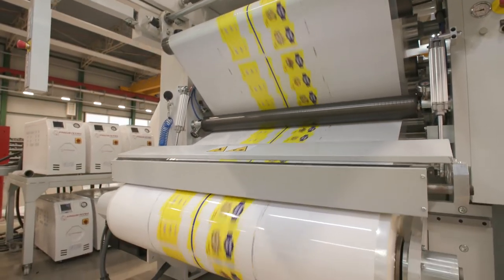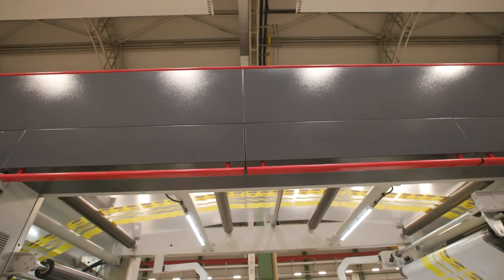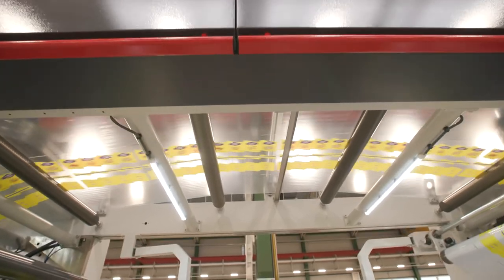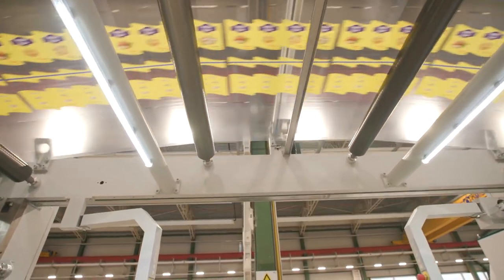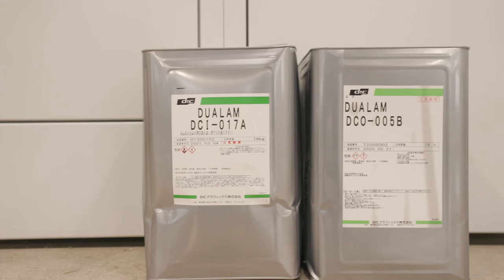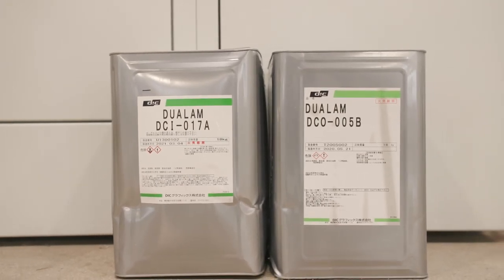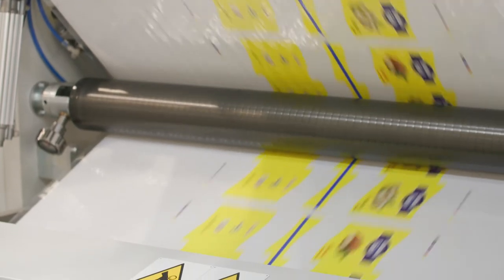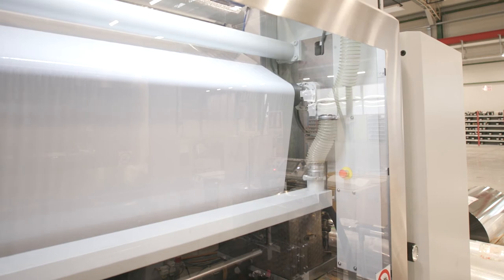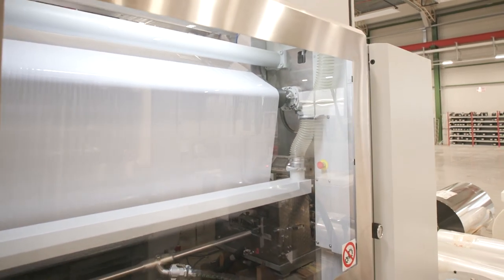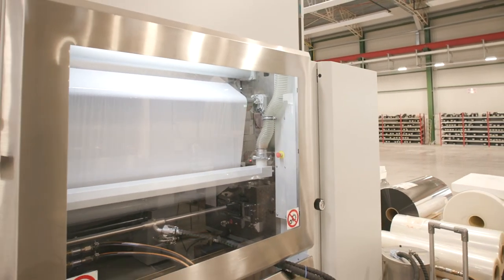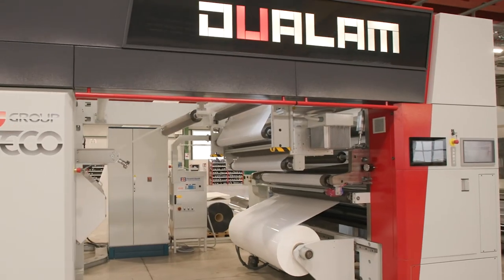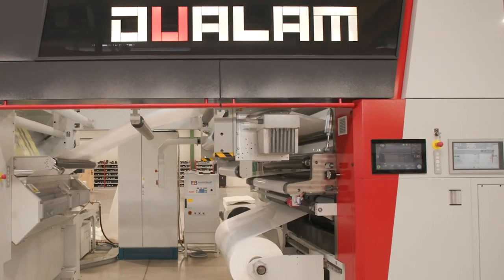The coupling of the two films was achieved by using the Dualam lamination technique, which, thanks to the dedicated Dualam DCI017A and DCO-005B inks, characterized by fast polymerization and high wettability, significantly reduces the non-polymer part of the structure so that it can be more easily recycled and increases the quality of the recycled product at the end of the packaging life